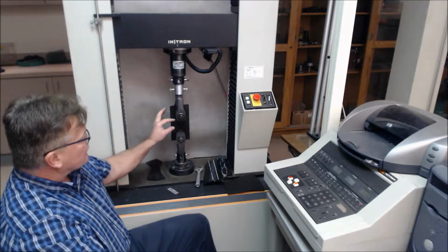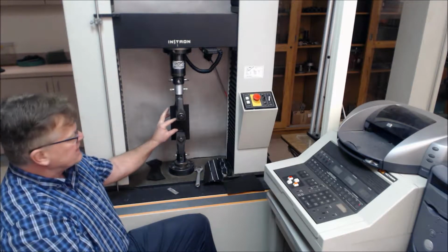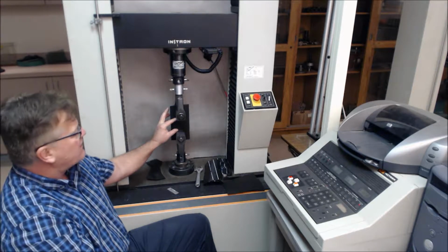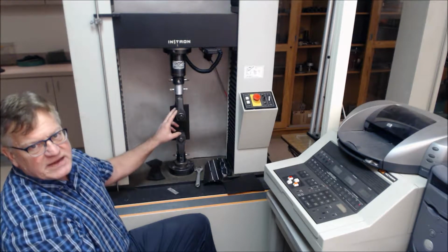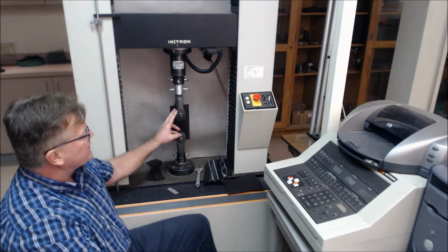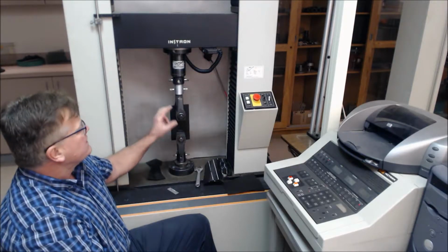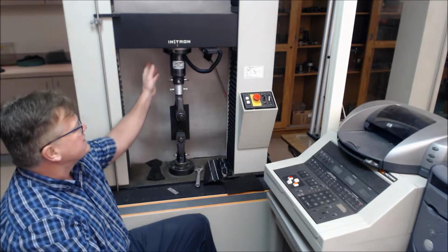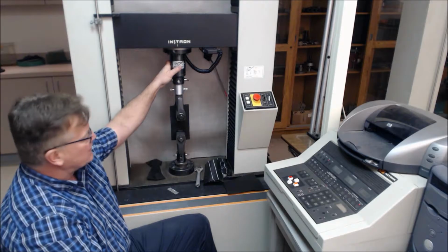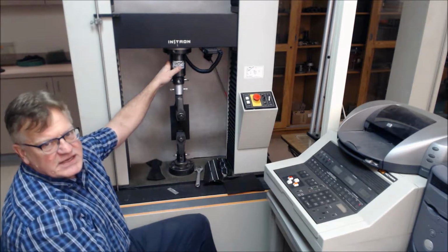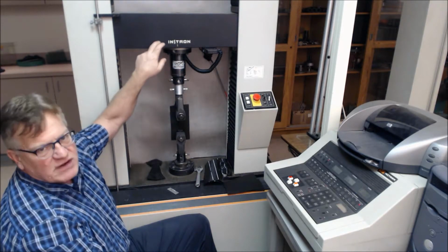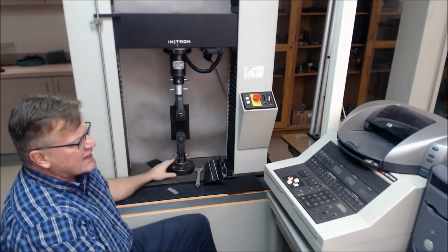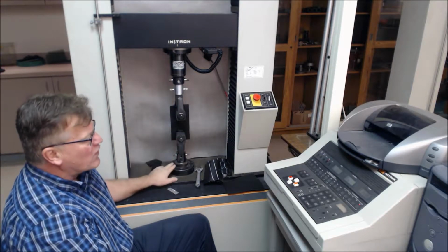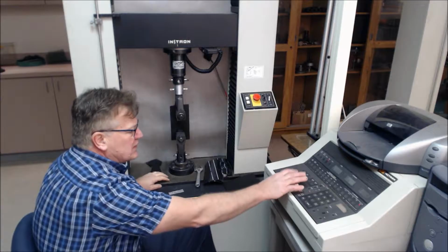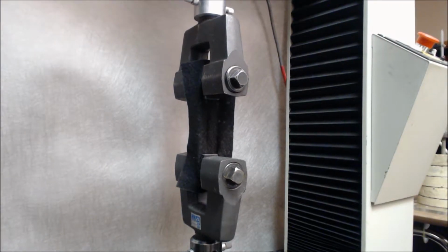The grip separation is 3 inches or 75 millimeters, and the speed is 12 inches per minute or 300 millimeters per minute. You're on a continuous rate of extension. You're going to measure load off of the load cell, and deflection is off of the machine's crosshead travel. This is all set up and ready to go. This is the non-woven textile. We will start the test.